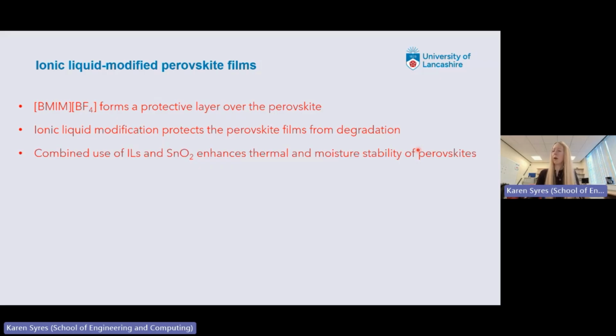So, okay, a little summary then of ionic liquid modified perovskite films, as I'm at the end now. We found that the BMIM BF4 formed a protective layer over the perovskite. Like I say, I've not shown all the data here. The ionic liquids protect the perovskite films from degradation. And we also found that the tin oxide did enhance the stability of the perovskites as well. So this is a project that's ongoing. I've got a PhD student at the moment who is continuing with this research.